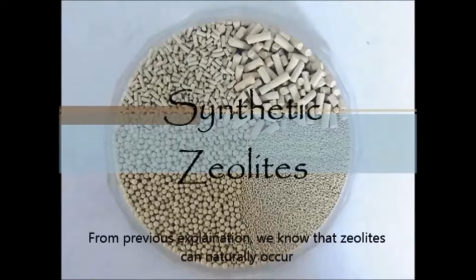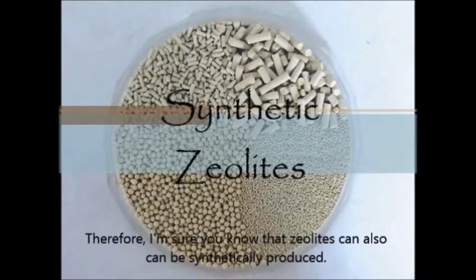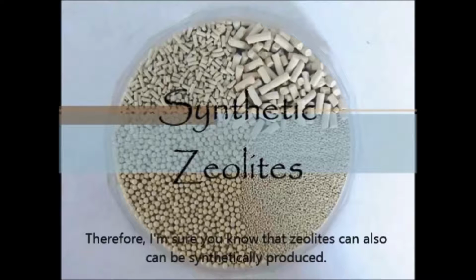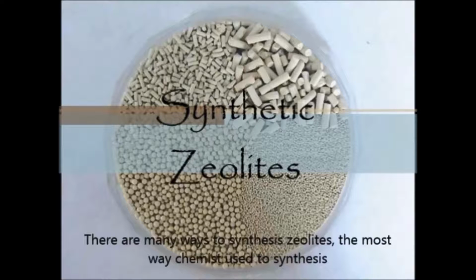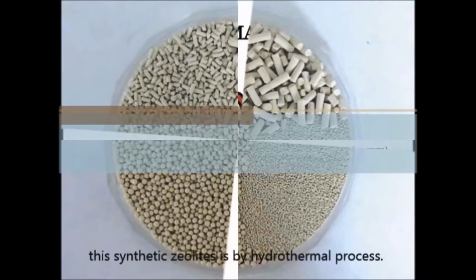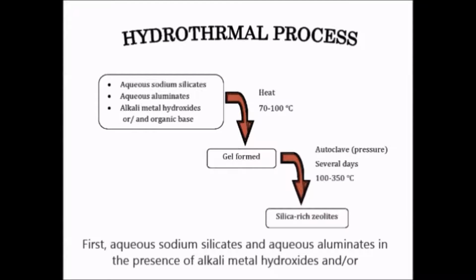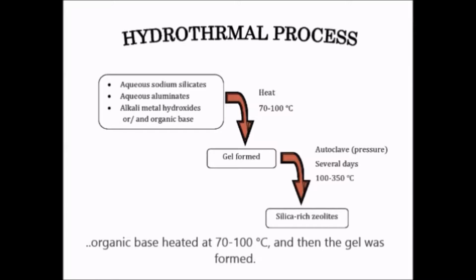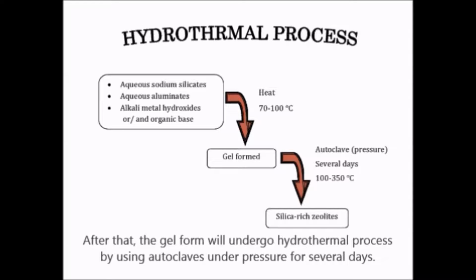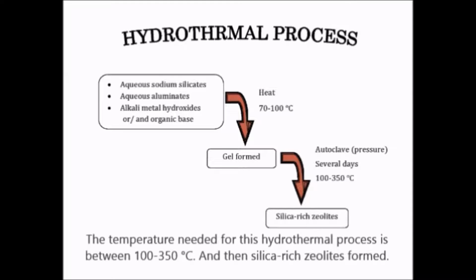From the previous explanation, we know that zeolites can occur naturally. Therefore, I'm sure you know that zeolites can also be synthetically produced. There are many ways to synthesize zeolites. The most common way chemists synthesize these synthetic zeolites is by the hydrothermal process. First, aqueous sodium silicates and aqueous aluminates in the presence of alkali metal hydroxides and or organic base are heated at 70 to 100 Celsius, and then a gel is formed. After that, the gel will undergo a hydrothermal process using an autoclave under pressure for several days. The temperature needed for this hydrothermal process is between 100 to 350 Celsius, and then silica-rich zeolite is formed.